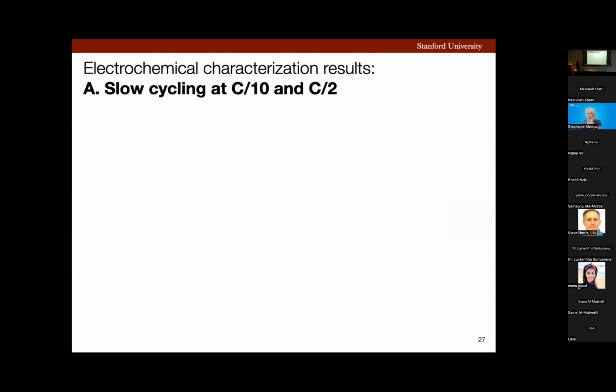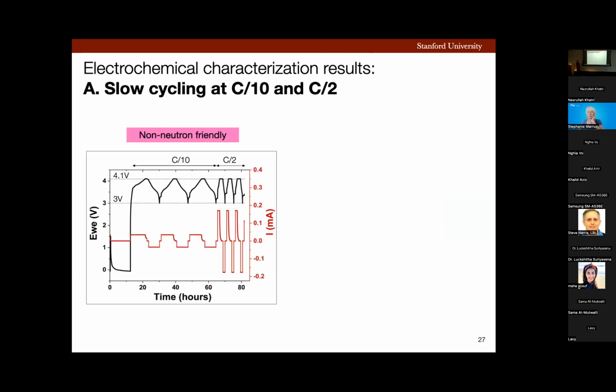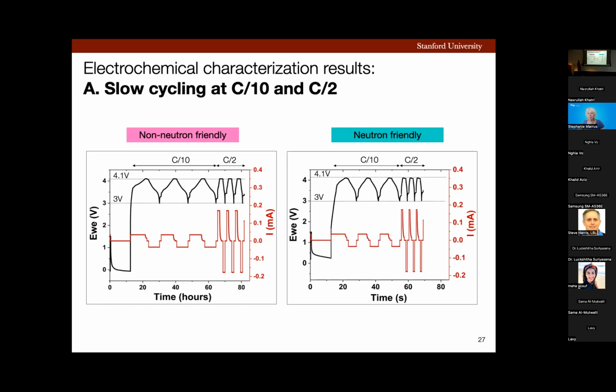Next, I tested the electrochemical performance of my battery. So here I'll be showing you the performance of my battery in comparison to a standard battery. Now let's see how these batteries perform in slow cycling, which is at C/10 or C/2, a very low current, if you look here. So here I'm showing potential and current versus time plot. And as you can see, these batteries cycle between 3 and 4.1 volts. Now let's compare the electrochemical signature of my developed battery. You would notice that these two signatures look pretty similar to each other, which means that my battery performed okay under slow cycling.